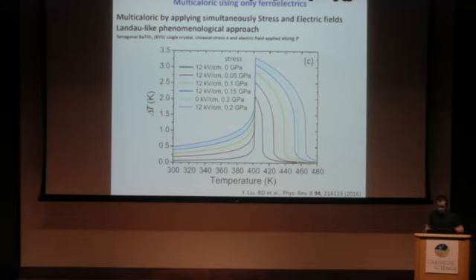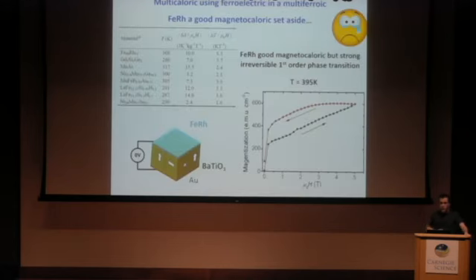Something that we did in the multicaloric, for instance, is to take this iron rhodium system. It's a magnetic system. It's a very nice magnetocaloric system. The problem of this guy, first, it's expensive, as I used to say, but also it has this first order phase transition. This is the magnetization as a function of the magnetic field, and you see that we have a huge first order phase transition, and if you want to cycle, you have a lot of losses in that case. So you have to find a solution.